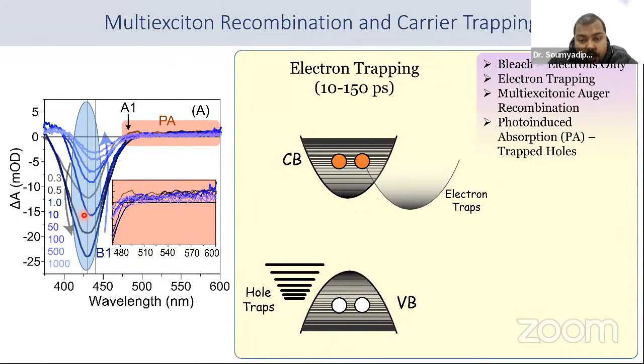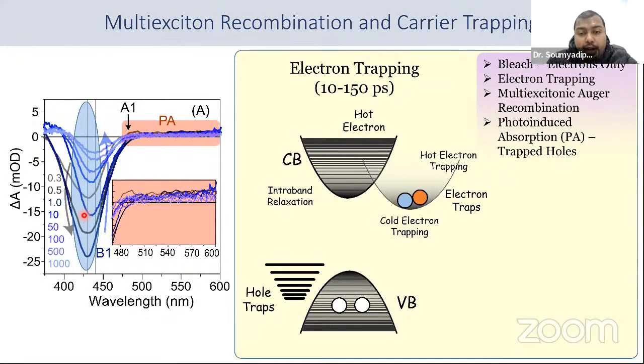Now, what happens when we are exciting? The electron goes to the conduction band, and those electrons are known as hot electrons. Then the hot electrons can directly go to the electron traps, which is known as hot electron trapping. Or the hot electrons get intraband relaxation, and then from the relaxed state, although it's in an excited state, it can go to the electron traps, and this is known as cold electron trapping. So these are the trapping processes that are happening, and you can see that from the kinetics of this bleach,